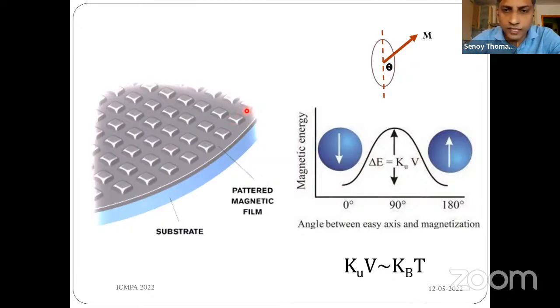The reason is that if you decrease the volume below a critical volume, then the anisotropy energy barrier KuV will get equated to the thermal energy kBT of the system, and the thermal energy will be sufficient to flip the magnetization direction. So if you decrease the volume below some critical volume, the magnetization within these individual elements is no more thermally stable, or one could say the information which we write is no more thermally stable because of the dominance of the thermal energy. This is a serious issue, well known as the superparamagnetic limit in the magnetic recording industry.